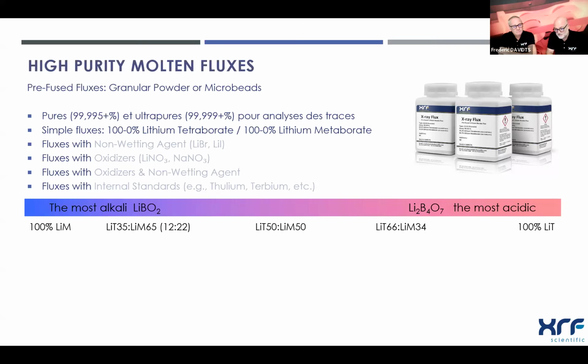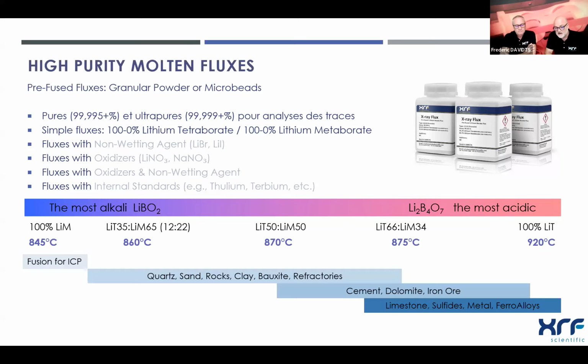The fluxes are characterized by their acidic or alkali character. So, for example, lithium metaborate is the most alkali flux, and lithium tetraborate is the most acidic. But also, you will use the flux in function of their fusion melting temperature, because you want to keep as much as possible the volatiles in the sample. And so, of course, the lower the temperature, the better it is. And of course, you can see that each type of flux mixture is more adapted to specific materials.